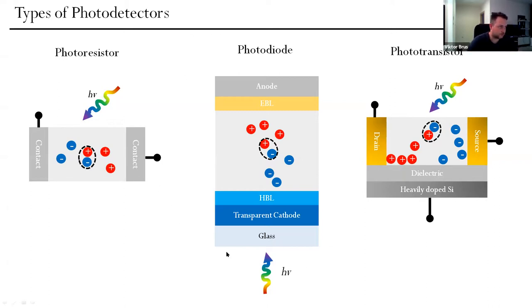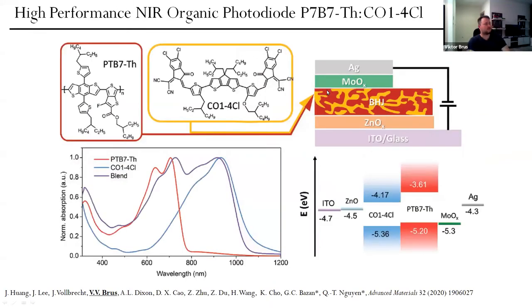So we focus here on organic photodetectors. We analyze them in the scope of this photodiode architecture. So we picked up a narrow band gap non-fullerene acceptor, which absorbs light at quite long wavelengths, up to 1200, which is quite a unique feature because most organic semiconductors are wider band gap, so their absorption spectra are shifted towards the shorter wavelength region. There was a task from Mitsubishi Chemicals to make a near IR photodiode sensitive at 960 nanometers. So that's why we had to use a narrow band gap non-fullerene acceptor.